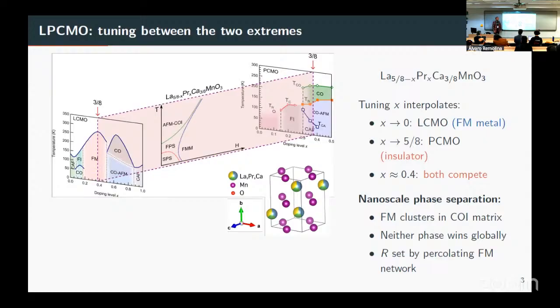And the idea is that if we can tune how much we have from both of them, we can have phase separation, and the phase separation will give you a metal insulator transition, a colossal metal insulator transition. And that's exactly what we got. So this is the phase diagram of one of the parent components. This is the other one. And then if we mix these two by a specific ratio of 5:8, we get something that looks like